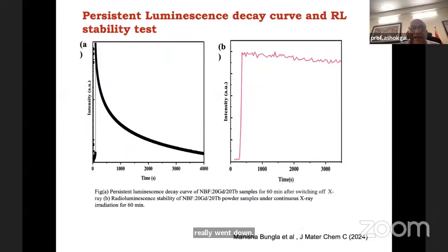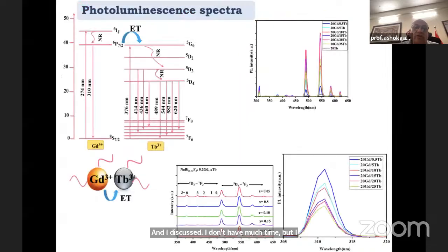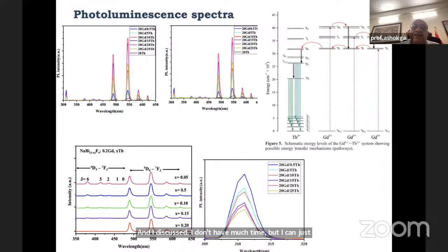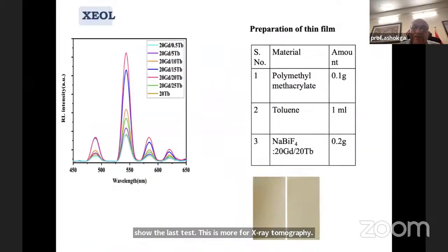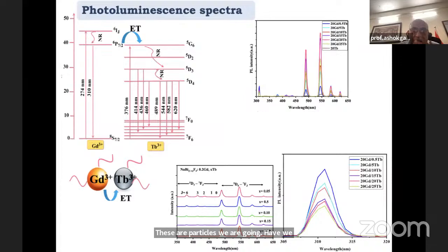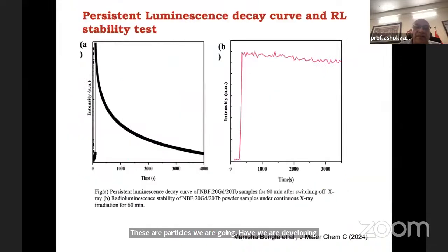I don't have much time, but I can just show the last test. This is more for X-ray tomography. These are particles we are developing, which, when injected, give you a persistent luminescence. That means you use X-rays for a very limited time, but the light which will come out from the body is much more delayed. So you don't want to use X-rays for a long time. You use only short pulses, right? But the decay, the luminescence, should be there for a longer time.